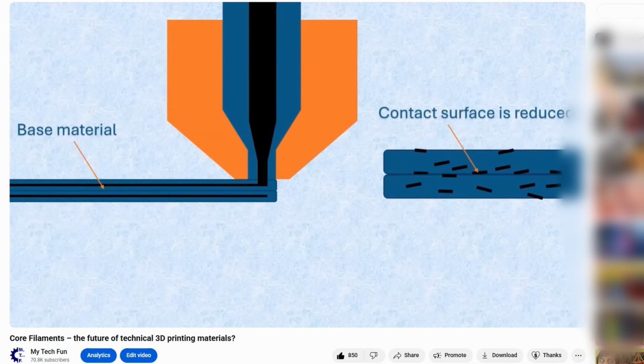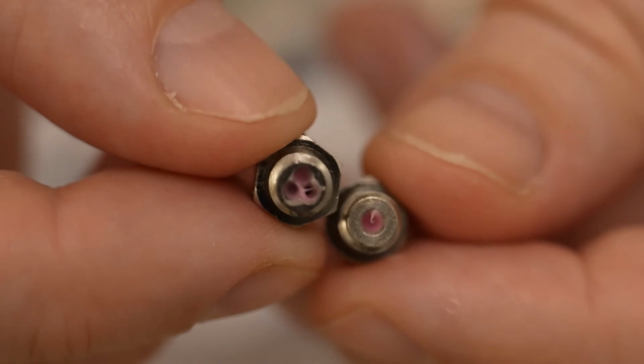Actually, there's one exception. If you use some kind of CHT-like nozzle, in that case we don't have that advantage of reduced nozzle wear, because the part is inside the core of that filament. But even in that case, it is recommended to use hardened steel or some kind of wear-resistant nozzle.